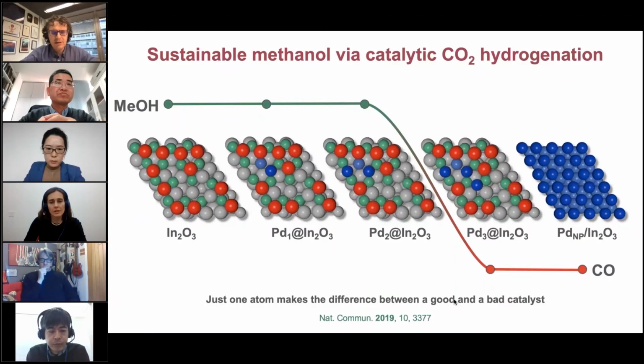One recent example to emphasize this is the design of promoters for the indium oxide catalyzed hydrogenation of carbon dioxide to methanol. You can see pure indium oxide on the left is extremely selective to methanol, but exhibits limited activity due to impeded hydrogen activation. The addition of palladium invigorates this step, increasing the CO2 conversion, but in contrast, shifts the selectivity from producing methanol to CO due to the reverse water-gas shift reaction.